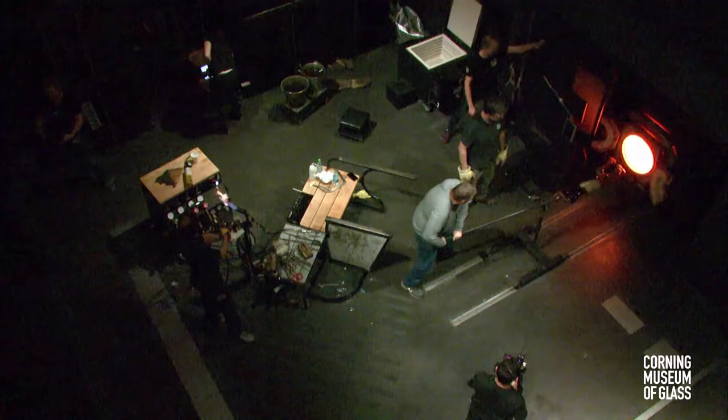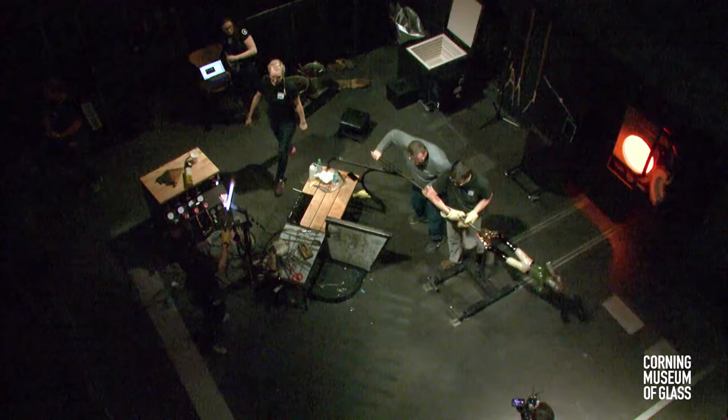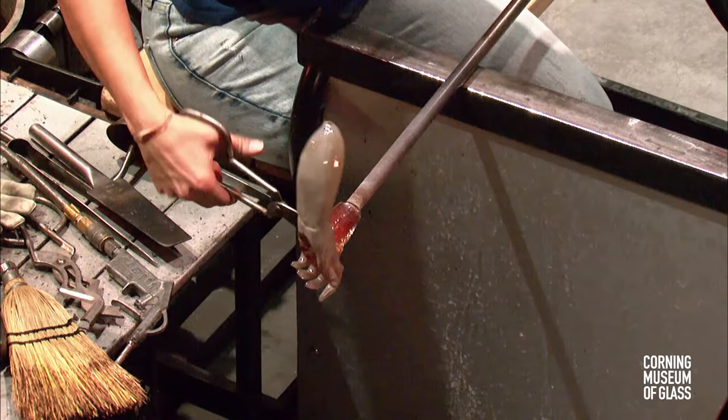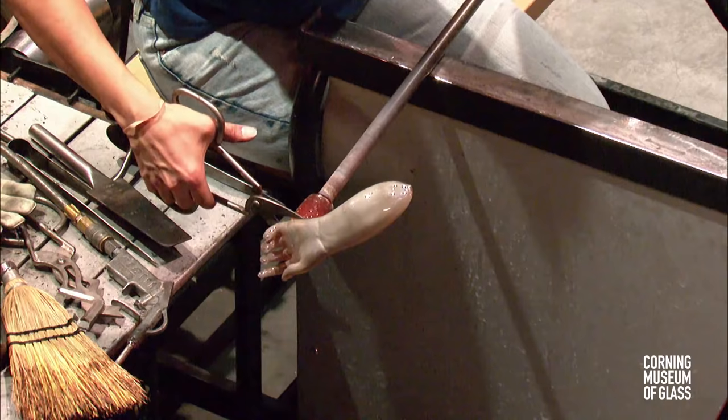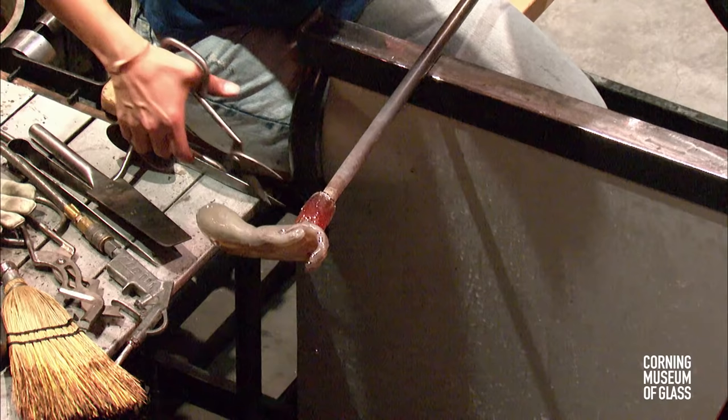The belly is not solid, but it's thicker. You know, you think about the dress shirt where it's tucked into the pants. That's two thick sections of glass that are coming together. That creates mass. You think about the belt that's wrapping around the hips of the bunny rabbit, the belt buckle. All of those things are adding some thickness. And so that's probably, I would guess, where the belt buckle is going to be one of the thicker areas of the object. But you know, no area of this object is more than a few inches thick, so we feel like 45 hours is probably safe.